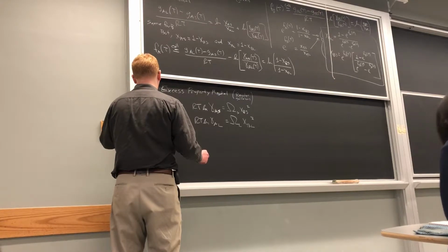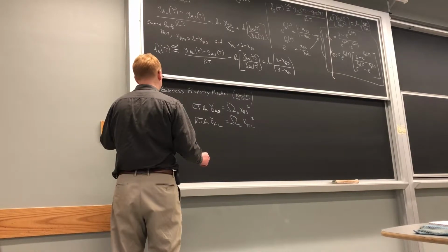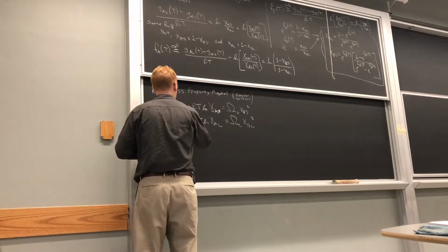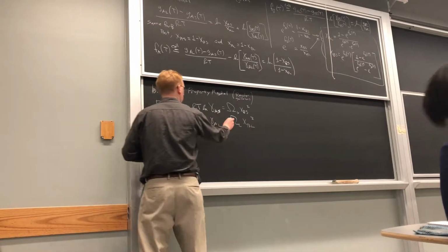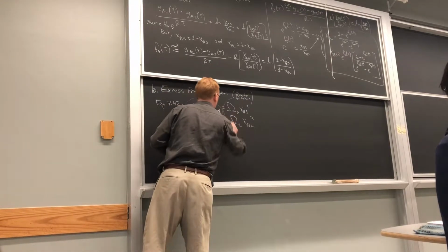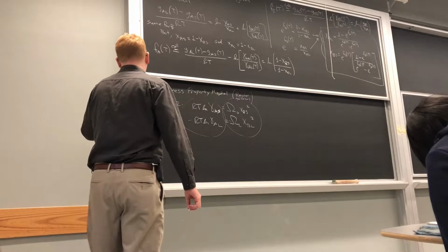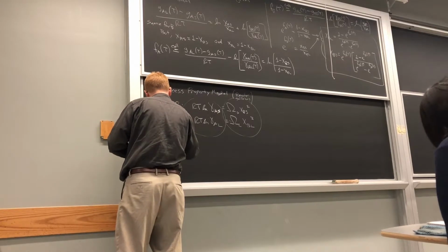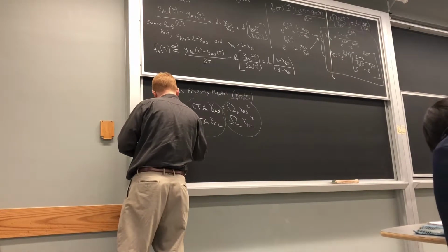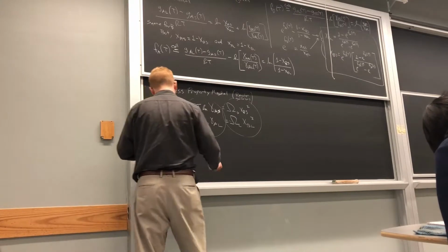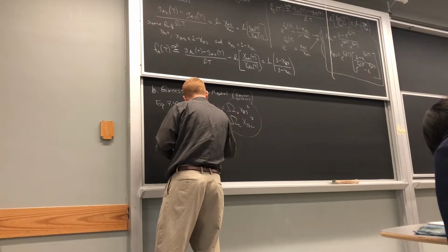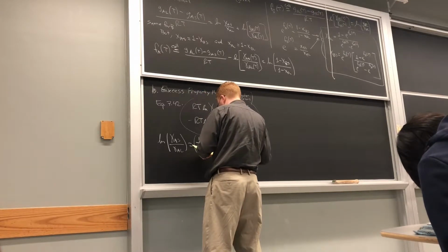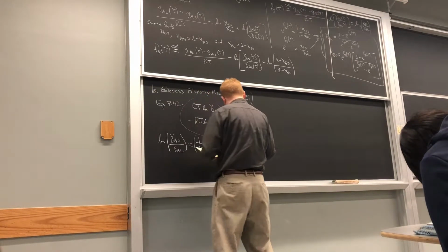Okay. So then what we're going to do is subtract these terms, one from the other. So I'm going to go ahead here and say minus and minus, and add this side, add this side. And then I'm going to factor out the RT. So we're going to get natural log of gamma AS over gamma AL is equal to 1 over RT times the difference in the regular solution terms for the solid first and then the liquid.